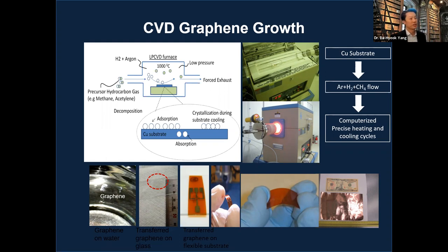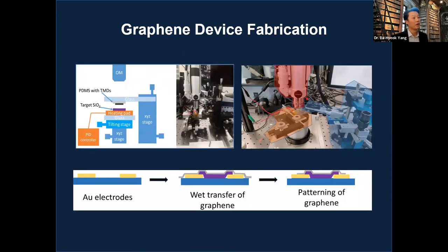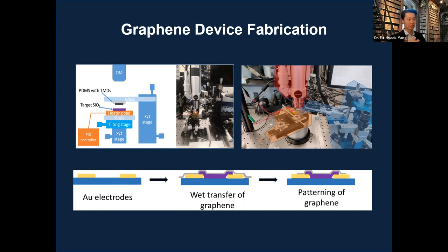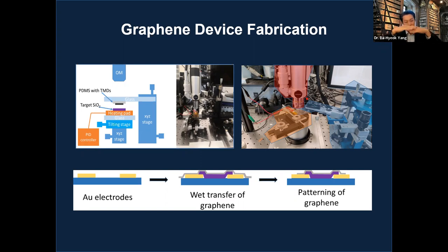After growth, you must fabricate structures before characterization. In practice, you need to apply hBN, connect electrodes, perform electron-beam lithography and patterning, then transfer — multiple steps. We use a custom-designed alignment and transfer stage to transfer 2D materials and align them with sub-micron accuracy on top of each other.